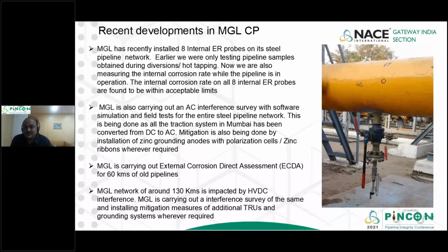It used to be a big challenge for us to monitor the pipelines, and to ensure that there isn't excessive voltage on the pipeline which can result in cathodic disbondment. But during the course of the last 6-7 years, the suburban trains have transitioned from DC to AC. So we are now done with DC interference. Now we have AC interference, but that is not a very big challenge compared to the DC interference which we used to have previously. Mitigation is done by installing zinc grounding anodes, with polarization cells and zinc ribbons wherever required.